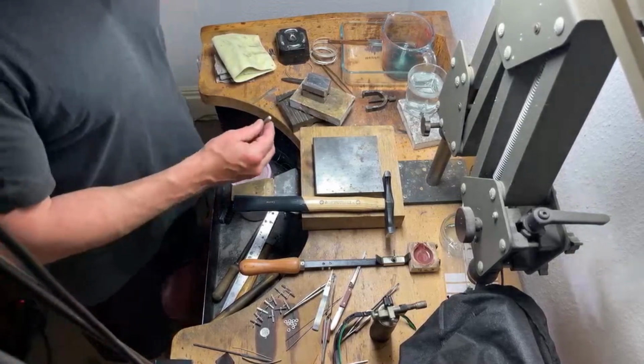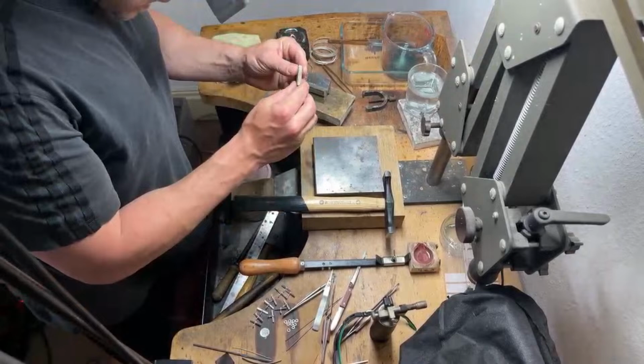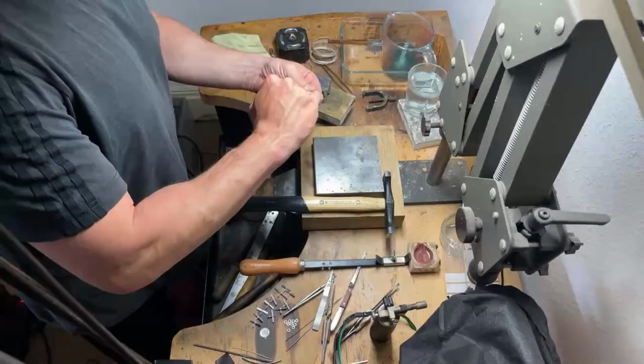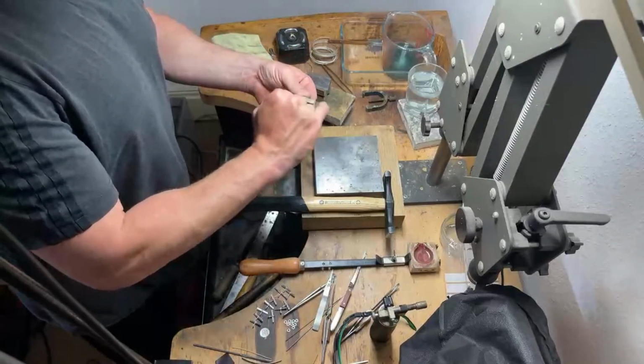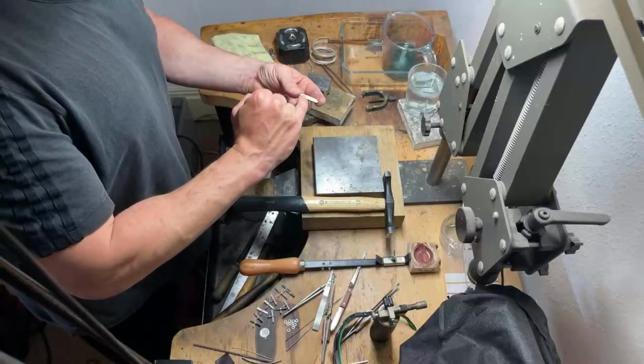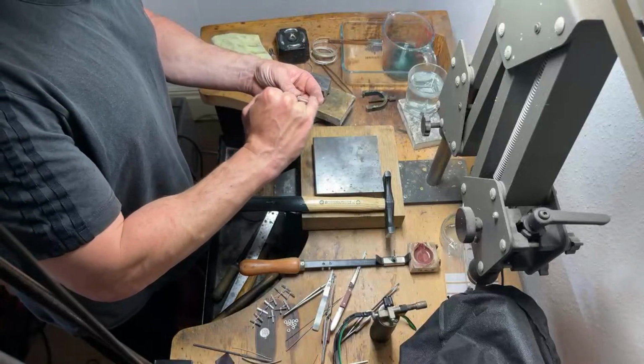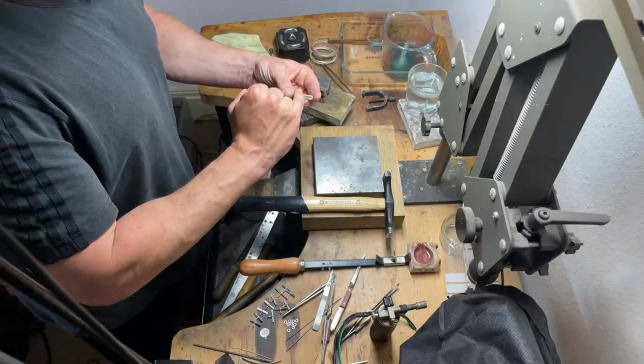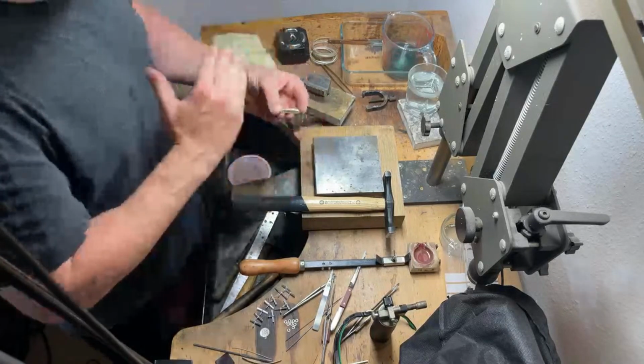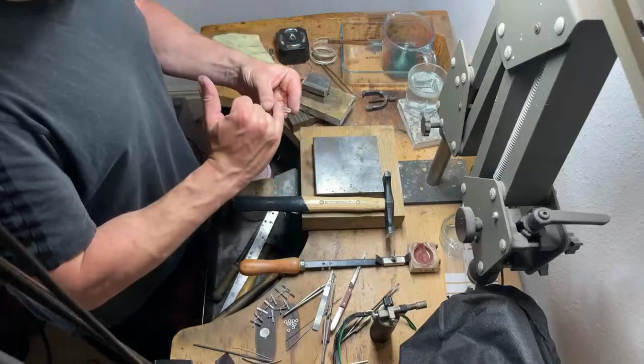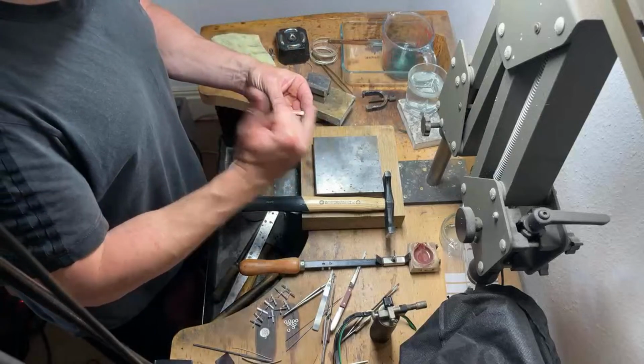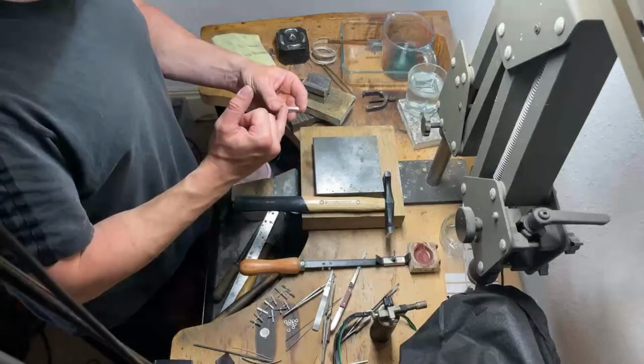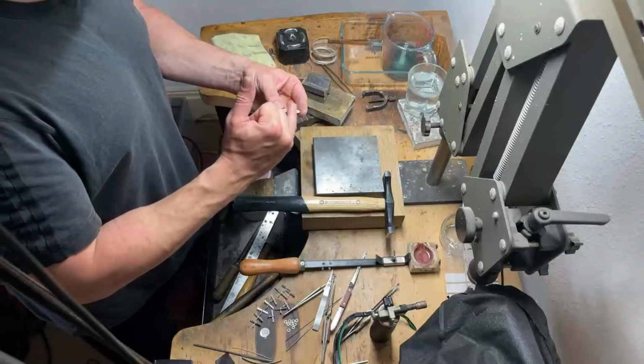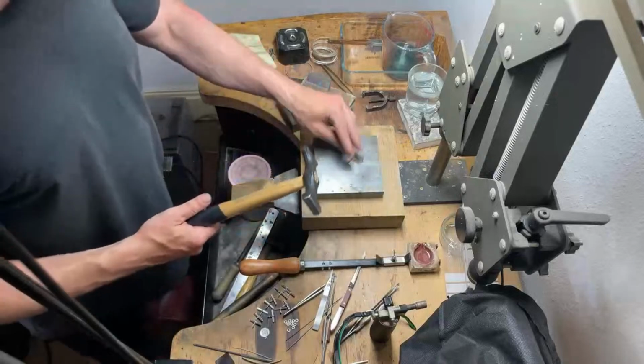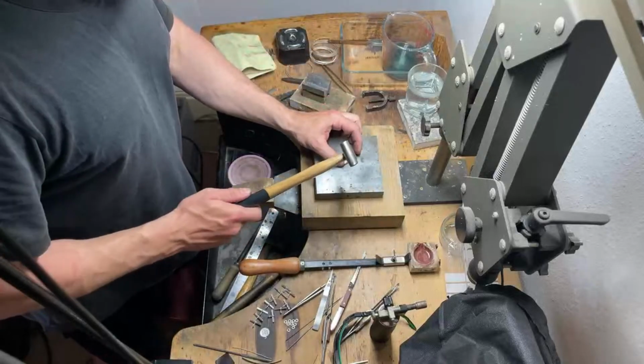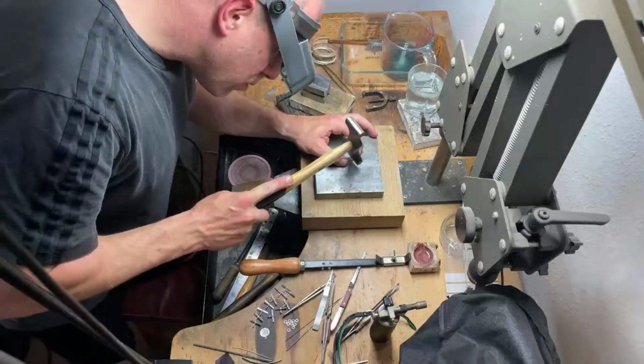What peening does seem to do is reduce cracking. Where the cracking normally appears when you're making wire is on the octagonal edges that the rolling mill creates. If cracking is going to appear, that's where it appears. That's why I take it back to the squared off. If you only do it once, because it only reduces about 0.4 of a mil every time, you're not actually peening all of those edges. And all peening is a series of small hammer blows.